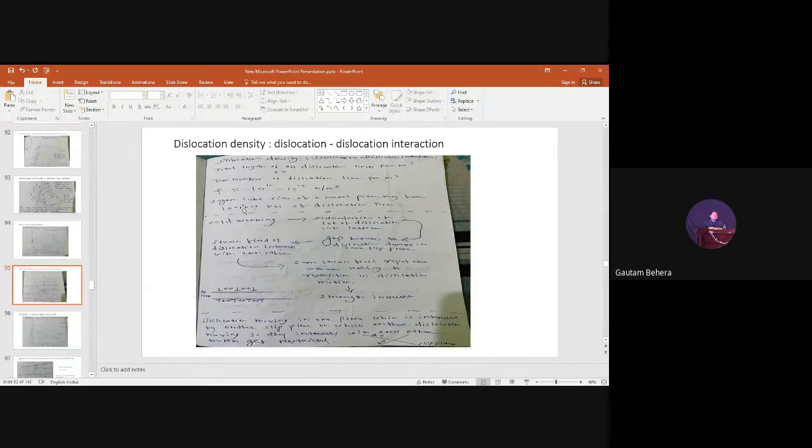Here there is a very interesting example. A sugar cube sized metal piece may have 1 lakh kilometer of dislocation line. It's very large. And how is the strengthening happening in this cold working process? This is a flow sheet. Cold working: if you do cold working on a metal or an alloy, what is happening? Introduction of a lot of dislocations into the lattice is happening.